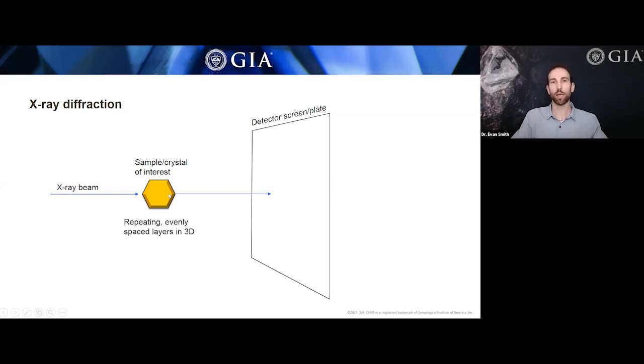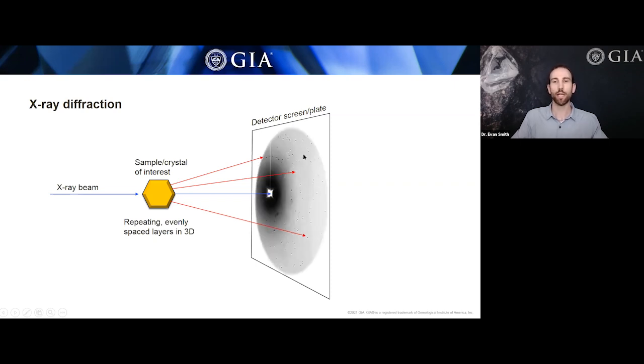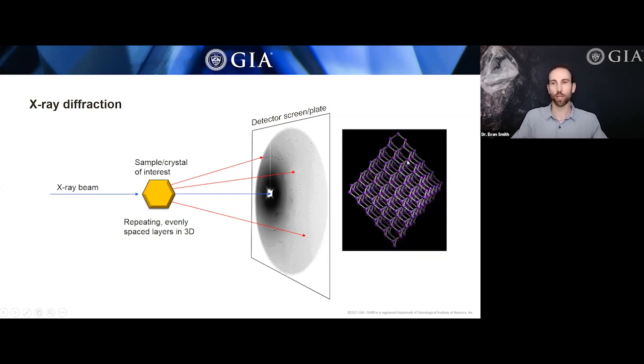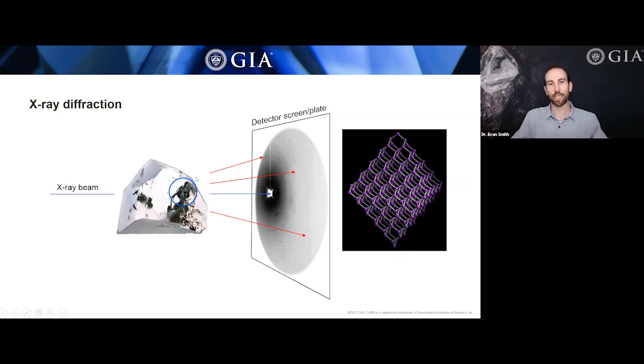But because this sample, if it's a crystal, has repeating evenly spaced layers in 3 dimensions, it will actually diffract some of this X-ray beam. So you'll get X-rays shooting off into different parts of this detector, and they can form a pattern. And this pattern contains direct information about the crystal structure, how the atoms are arranged in 3D. So this is what I did with our sample of diamond here, and specifically this altered inclusion within it. And this is what the data looks like.